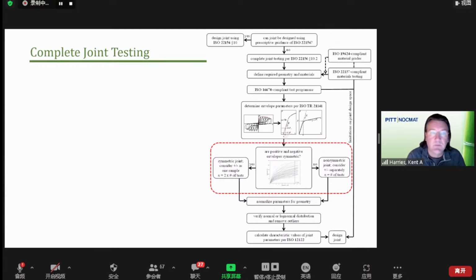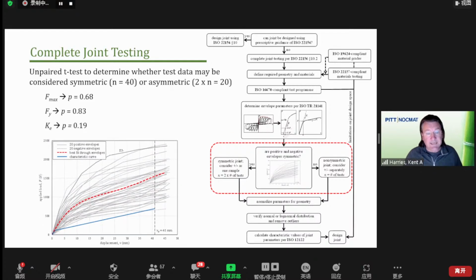That being the case, we're going to have 20 positive, 20 negative. And so we want to test this hypothesis. In our case, particularly, we want to see if we can treat both positive and negative together. So we do very simple statistics, an unpaired t-test, to compare the positive and negative cycles, the 20 positive, the 20 negative. And sure enough, in terms of all of the capacities that we're looking at, the positive and negative cycles are statistically the same.